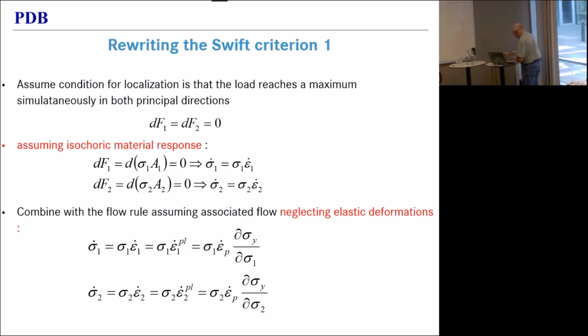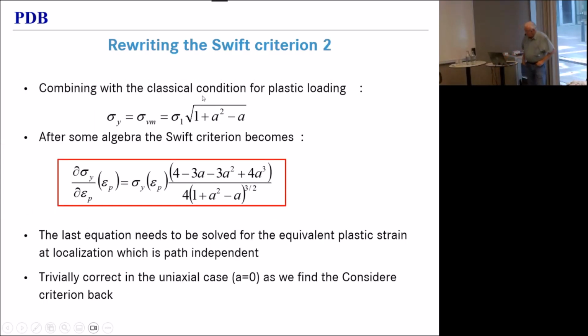The last thing you have to add are the classical plastic loading conditions, where we say that we're in a condition where the yield stress is equal to the von Mises stress. And you have to add the same thing with a dot, showing that we're actually evolving in a way that we stay on the yield surface. It then takes about 1 page of algebra, it's not very big, to derive the condition that expresses that simultaneous equilibrium of the two forces.